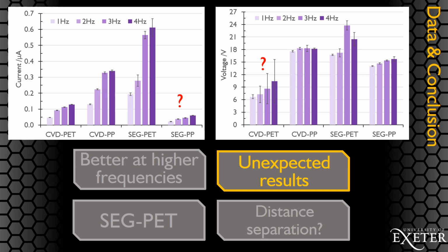According to preliminary experimentation and in the literature, CVD should carry charge better because of its uniform tri-layer structure. However, papers also exist suggesting CVD as inferior due to its energy-intensive process that also lacks scalability. SEG-PP also performed rather poorly in current data. A reason for this could be an absence of SEG on the device after the IPA transfer process. This would make the conductive travel path more difficult to traverse across the device.